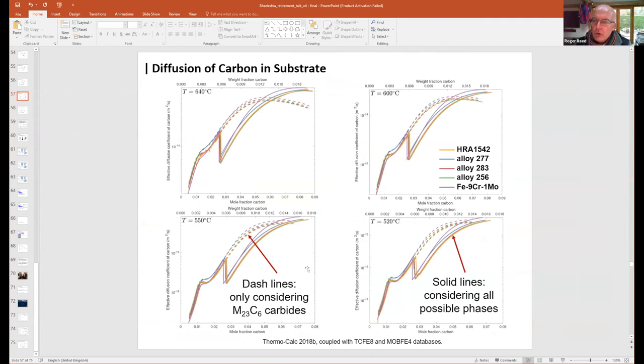I'm not sure of that, because of course these alloys are very close to the 9-chrome moly composition, which I guess was emerging from the Oak Ridge National Labs. I know that they did add silicon, because they found that this improved the oxidation resistance and also pushed up the chromium level a little bit. But I would imagine that in retrospect, one could radically alter the composition to give you a different one.